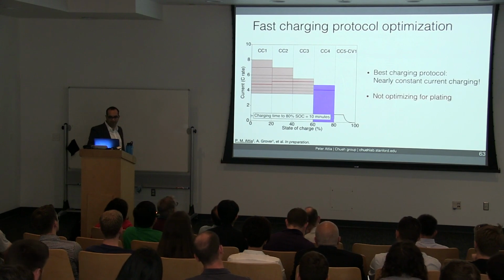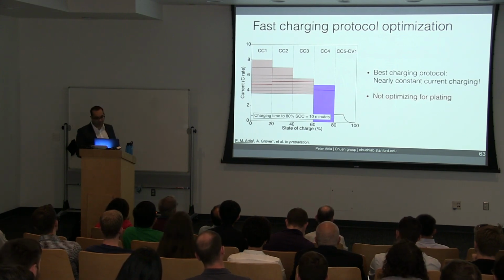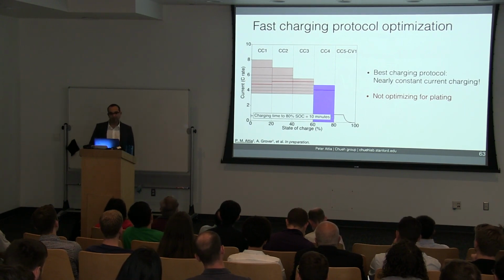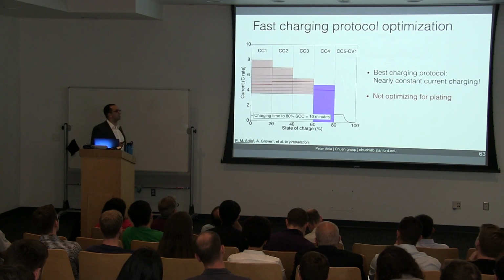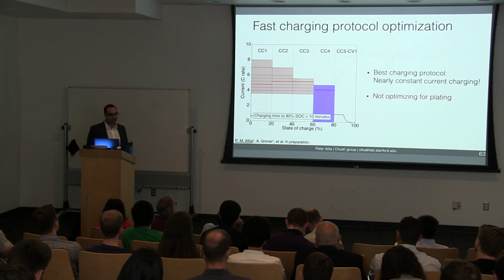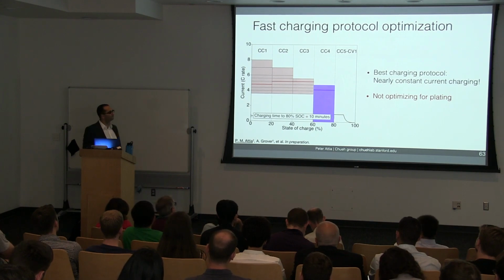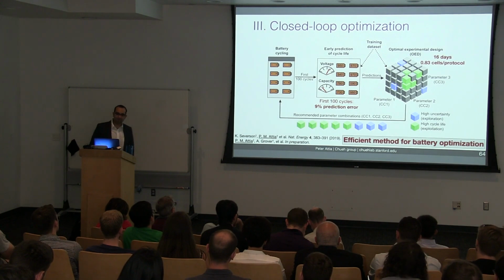We have some ideas, and I'd be happy to discuss them later, but what's clear here is that we're definitely not optimizing for plating. We find this pretty surprising given that plating is so widely reported during fast charging. Our best guess here is that constant current charging is an optimal strategy for minimizing heat generation. As SEI grows, it increases with increasing temperature. And this makes sense given the results from part 2.